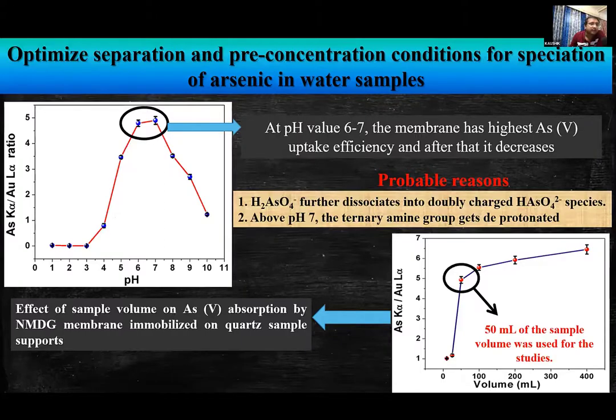Now, there are several factors that could affect the sorption of arsenic 5 species into the NMDG membrane. The first and utmost factor is the pH of the medium. It was seen that around pH 6 to 7, the membrane has the highest arsenic 5 uptake efficiency. After that, as you can see, the uptake of arsenic 5 steadily decreases.